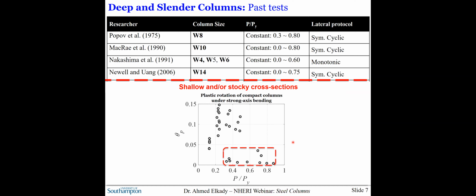Now, excluding the past 5 years or so, there has been a limited number of tests on compact wide-flange steel columns, essentially the ones you see summarized here. Those involved either shallow or stocky cross-section sizes that are not representative of those used in current practice. And although most of these tested columns had a robust cyclic performance, some still had limited ductility, even at moderate axial load levels.